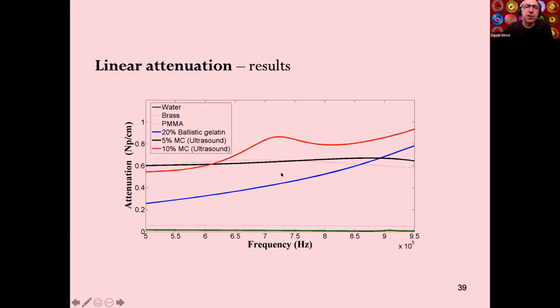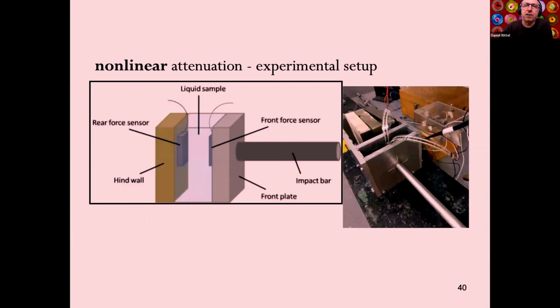And then you go to the gel. You go to ballistic gelatin, that's a well-known solid. And then you go to the gel, 5% in black, 10%. It's mostly water. You have to realize that this is mostly water. The 5% gel is water. And the linear ultrasonic attenuation is rather high. We will not pursue here the quantification of the complex moduli of the material. We just want to know the attenuation. So that's the linear attenuation.